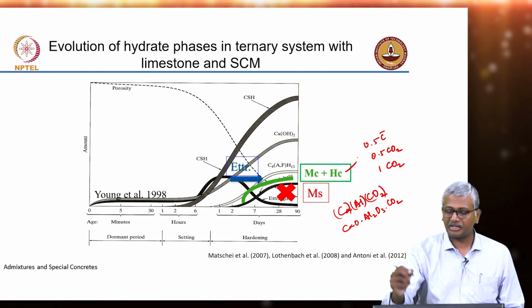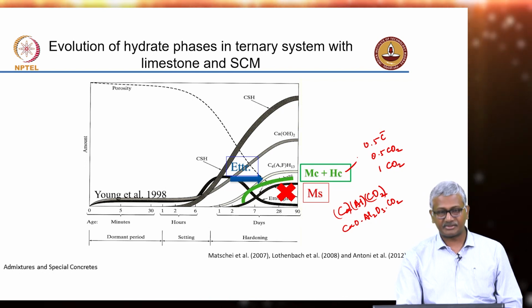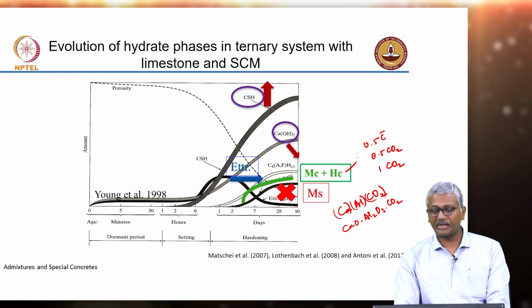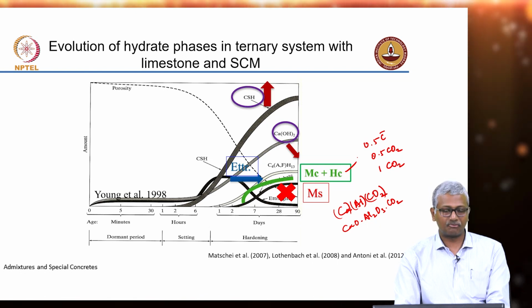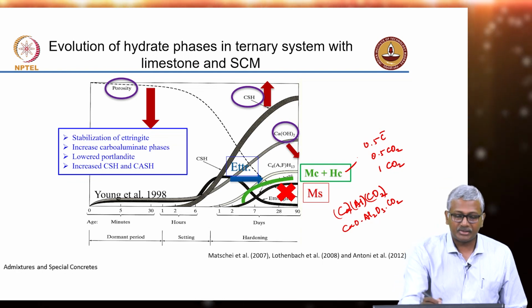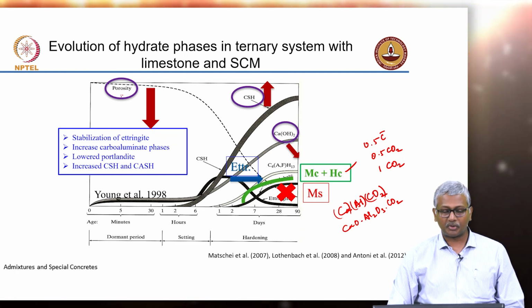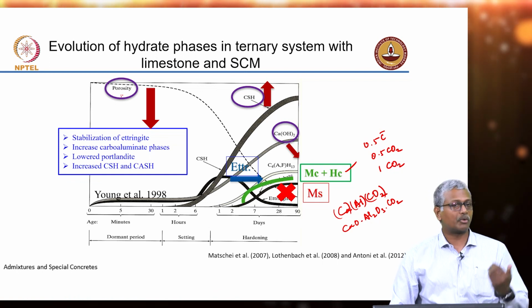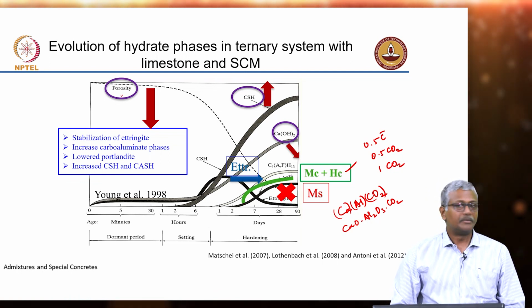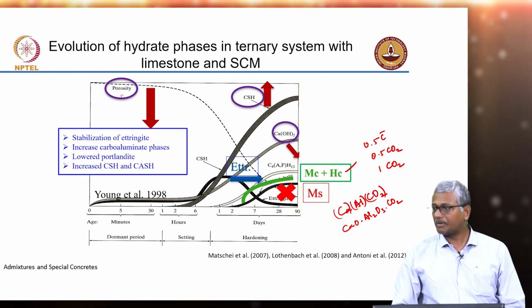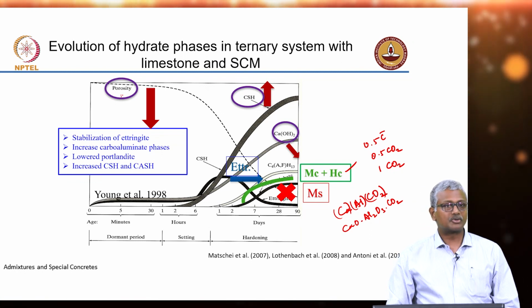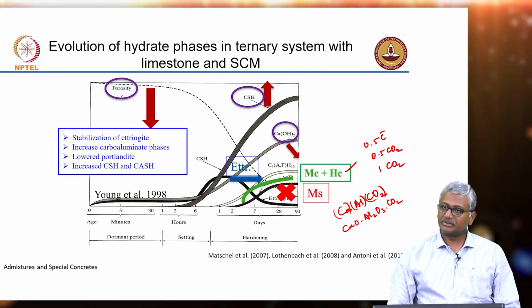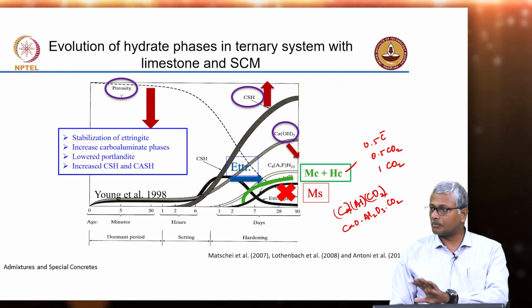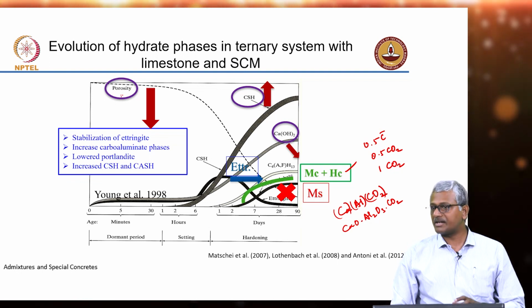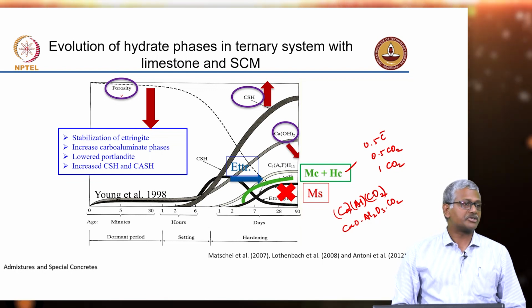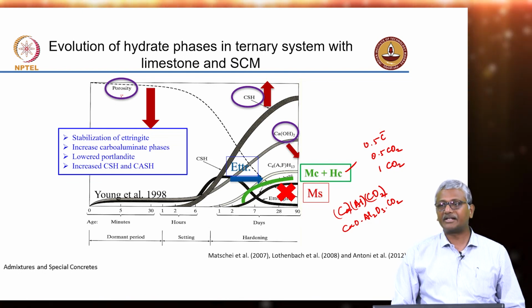So, you start forming carbo aluminate phases, which are then filling up more of the space that is available. You start consuming calcium hydroxide and increasing the CSH formation. So, in other words, you are causing the system to get lowered with respect to its porosity, and in general, lowering porosity will also lead to lowering the permeability of the system. Lower permeability implies better durability. Okay. So, generally the experimental results suggest that porosity reduction is not so much as to cause a major enhancement in strength, but the permeability reduction is significant, and that leads to a major enhancement in durability.